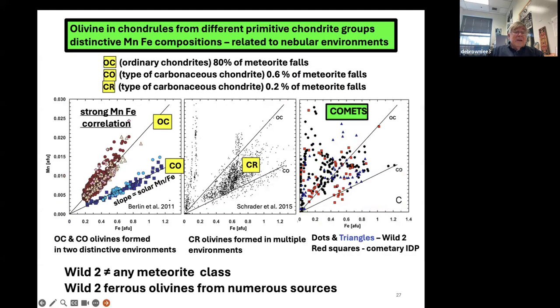On the left is the manganese and iron plot for olivine from ordinary chondrites and CO chondrites. There's a high correlation between manganese and iron because manganese, Mn2+, is substituting for Fe2+. The ordinary chondrites are higher than the CO, which is about the solar ratio for manganese and iron, because a major fraction of the iron is actually in metal, which manganese cannot fit into.